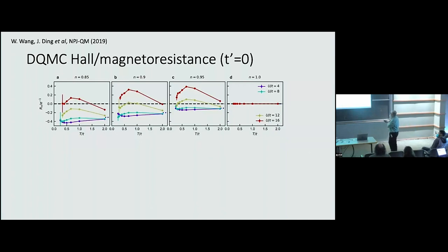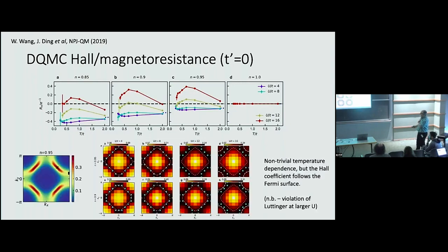But as one dopes off, you can see that there's a very strong temperature dependence, and in fact, it can even have several different crossings. And that is maybe what you might have expected, where you can go from hole to electron and so on. But the thing that was surprising is that that number and the temperature dependence really just follows from looking at the enclosed area of the Fermi surface. So even though it's a very strongly interacting problem, the topology of the Fermi surface really does tell you something about the Hall. At all temperatures. Yeah, because the Fermi surface changes with temperature.